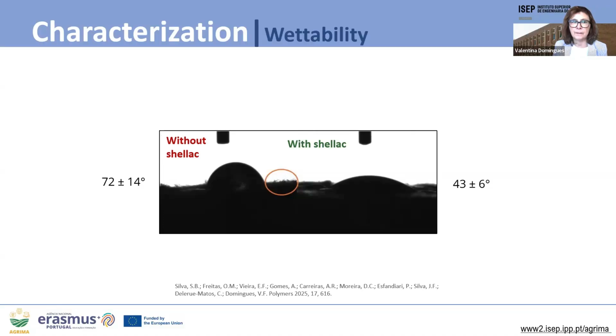The effect of adding shellac as a hydrophobic surface coating was studied by comparing one composite with shellac with another one without. The results show that the untreated composite had a higher contact angle. On the left, the angle was 72, compared to the composite treated with shellac that obtained an angle of 43. This suggests that the shellac-treated surface was more hydrophilic, contrary to initial expectation that shellac would enhance water resistance.